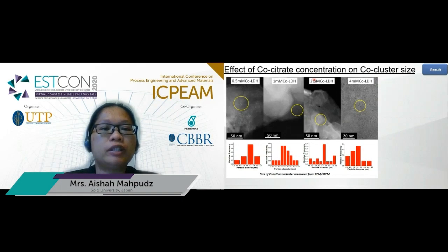In this slide, it shows the effect of cobalt citrate concentration used in the ion exchange on the cobalt cluster size. Here are the TEM images of all four samples, 0.5, 1, 2, and 4 millimolar. The yellow ring here highlights the cobalt particles that are identified using EDS. And from each image, we can see that the size of the cobalt nanocluster obtained increases when the concentration of cobalt citrate increases.